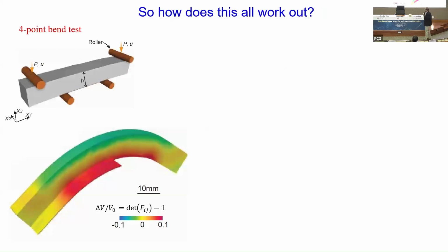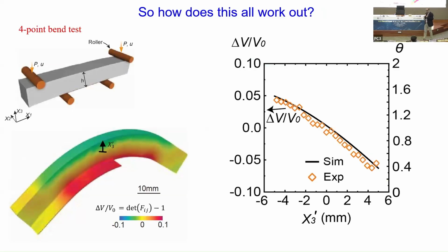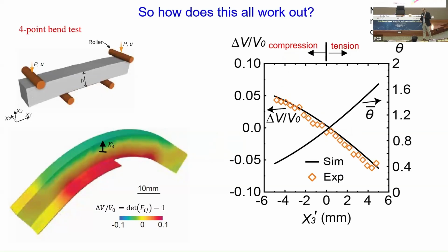So what happens when you actually solve this problem? Now that you've got yourself a consistent theory with this additional state variable, if you look at what it is predicting, it's predicting exactly what we were observing. On the compression side, the volume has increased, it's positive, and on the tension side, the volume has decreased, and the experiments and the simulations match. But the mobile phase concentration goes the opposite way: on the tension side, the mobile phase has increased, and on the compression side, the mobile phase has decreased. Very much like what we were measuring.